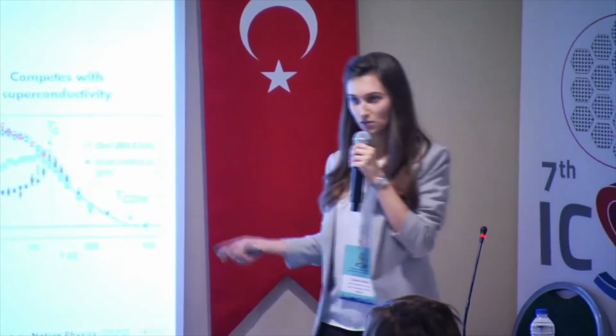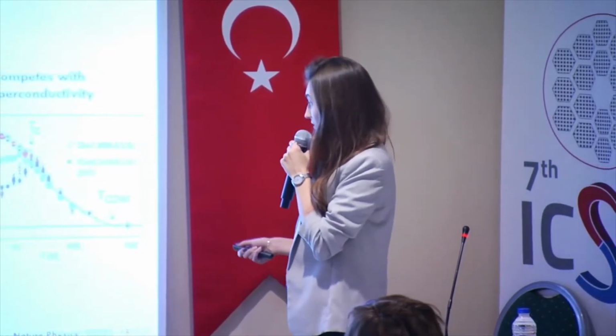But charge density wave order not only coexists with superconductivity, it also competes with superconductivity. It can be seen in this picture, where the intensity of the charge order is shown as a function of external magnetic field. This intensity is growing, while at the same time superconductivity is of course suppressed. So these two phenomena are competitive to each other. However, we don't clearly know the mechanism of this competition, and that's quite interesting. That's why we are still investigating charge density wave order intensively.